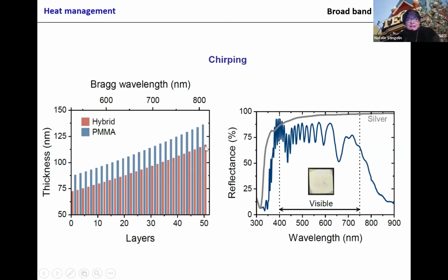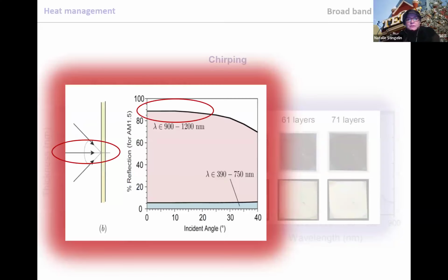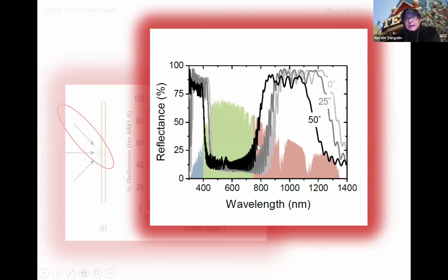You start to lose the second order reflections, and therefore we can get from 800 to 1400. In case we add more layers, we could push it further, or if we simply start at 900 and go to thicker layers, we push this to like 1600, 1800. The beauty is we can design it. If you tell me you want the reflection at 2 microns, we can design the mirror so it reflects at 2 microns.